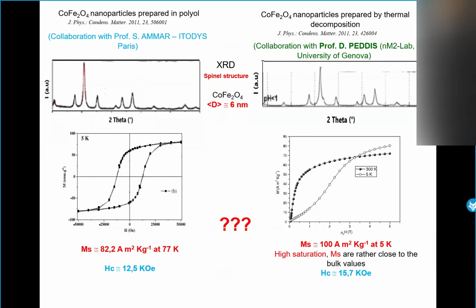A comparative study between two cobalt ferrites prepared by two different chemical syntheses. The first was obtained by polyol and the second by thermal decomposition. The XRD showed they have a similar spinel crystallographic structure, and also a similar size. Now if we look at the magnetic measurement for the particles prepared by thermal decomposition, we obtain a very high saturation magnetization, rather close to the bulk values, and also a very high coercive field. So what is the difference in behavior between these similar magnetic nanoparticles? For that, we applied an external field.